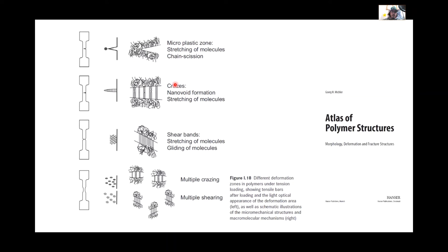One terminology that I want you to pay attention to is crazes. So you start having these craze cracks forming, and crazing is really important to grasp. Anytime you bend a polymer and you see white, that's called strain whitening, and that's due to a bunch of craze cracks. And we'll see an example here later on. But we start seeing the formation of these crazes.